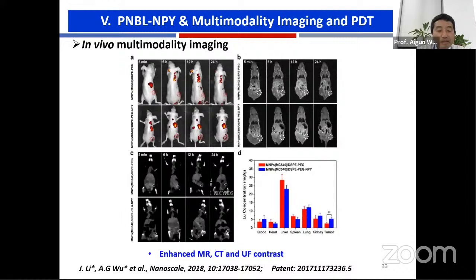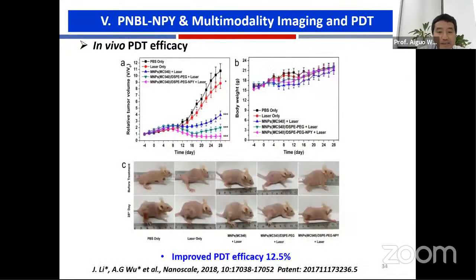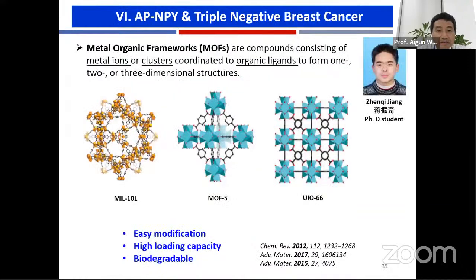So we found it definitely can enhance the MRI, CT, and upconversion fluorescence contrast there, and get a very good signal enhancement. And also we found it improved the photodynamic efficiency by about 12% for the tumor-bearing mice.